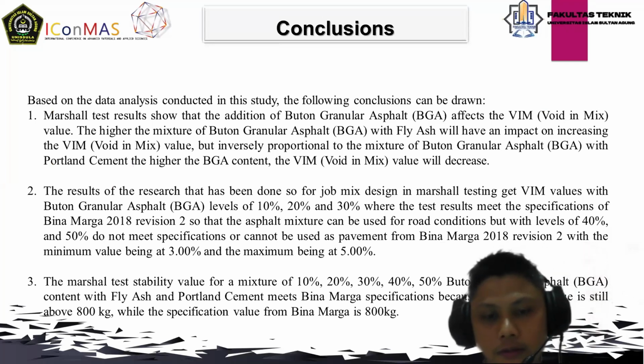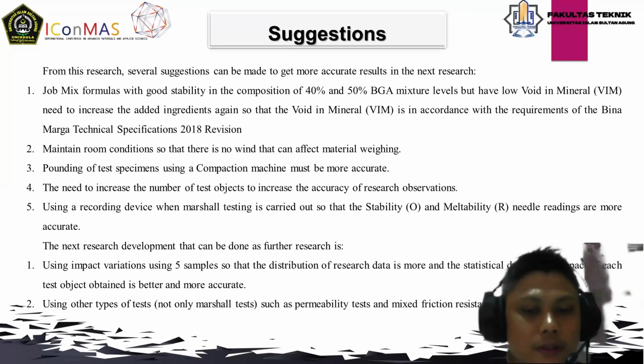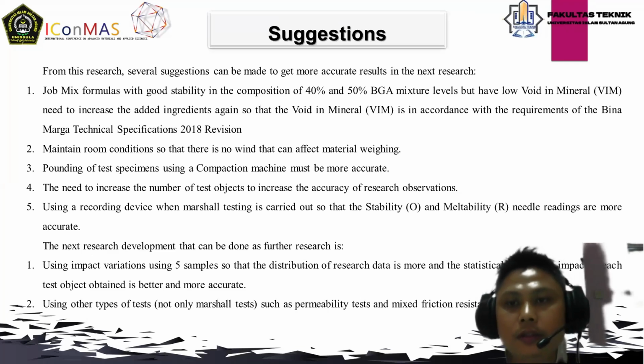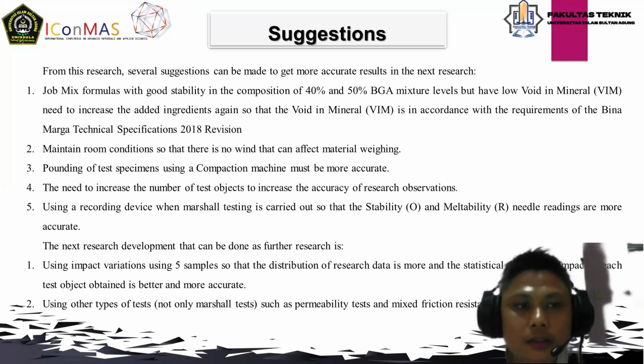What's the suggestion for me? The suggestion one is the Job Mix formula will have good stability for the composition 40% and 50% BGA level, but low for mineral, so it needs to increase the mineral according to the requirement for the Bina Marga reference. The number 2 for my suggestion is to maintain room condition, so that we do not affect material weighing, and the pounding of the specimen using a compaction machine must be accurate.